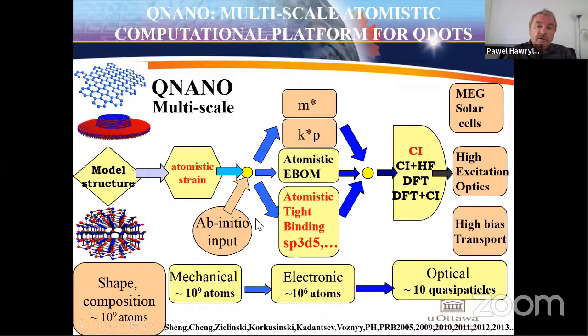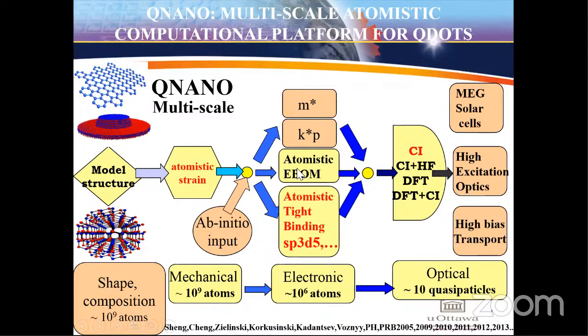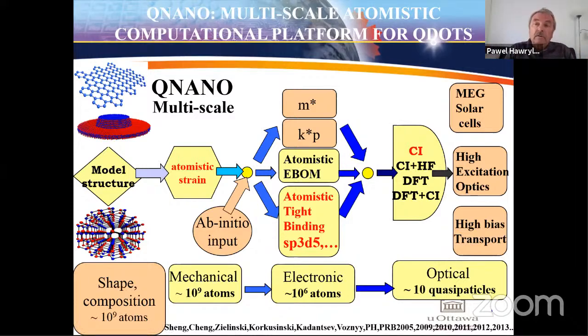Then we use a lot of ab initio input to compute one electron properties. And the nice thing is that we do this in atomistic tight binding scheme, but also in k.p, in effective mass, so that we have different levels of approximation for one electron properties. And while strain calculations can be carried out up to about 1 billion atoms, the electronic properties are limited to something of the order of million atoms, with about 20 orbitals per atom for sp3d5s*. And this is a fairly complex calculation in itself.